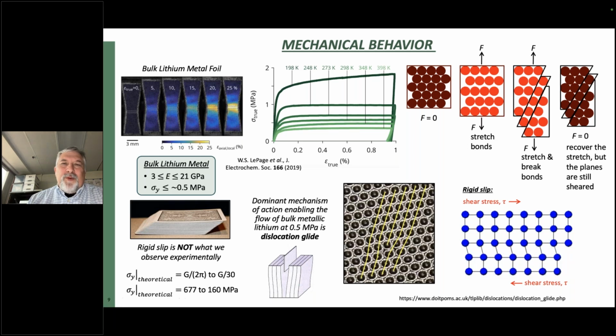Rigid slip requires simultaneously breaking all those bonds along the glide plane, and that obviously requires a lot of energy, hence these high theoretical strength limits associated with rigid slip. In comparison, dislocation glide operates very differently. We achieve the exact same outcome, but it only requires breaking the bonds along the dislocation core. That mechanism requires much less energy, and that energy is consistent with what we observe experimentally up here.